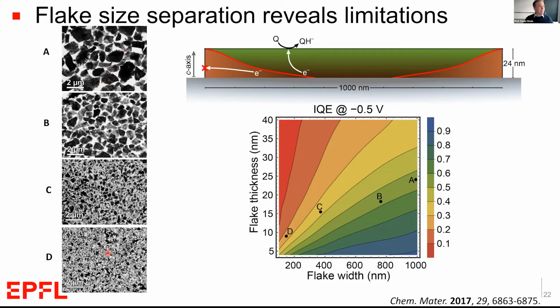In fact, there is that correlation between the length and the width that we see when we do the ultrasonication, which means that we are never able to achieve flake sizes with a very wide width and a very thin thickness. Our theoretical transport calculations, given this anisotropic transport in these materials, suggest that what we need to achieve are flakes that are very wide but very thin, and that will reduce the transport to these recombination sites at the edge. But we can't access that region using the ultrasonic-based exfoliation, and that's just due to the intrinsic material properties. So we have to find a different way to exfoliate these types of materials.